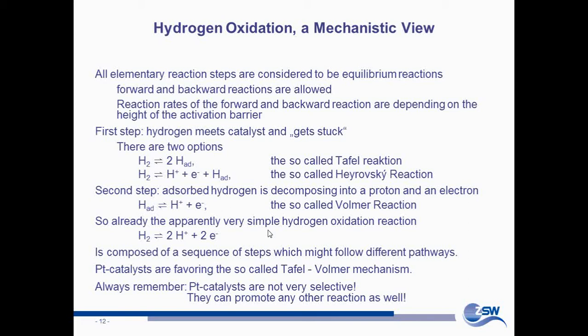But you can easily disturb that two-step mechanism by just messing up the surface with carbon monoxide, with sulfur, with everything else that bonds more strongly to the catalytic surface. You can always think of a catalyst as a go-between. So it arranges a marriage, but it doesn't take part in it, right?